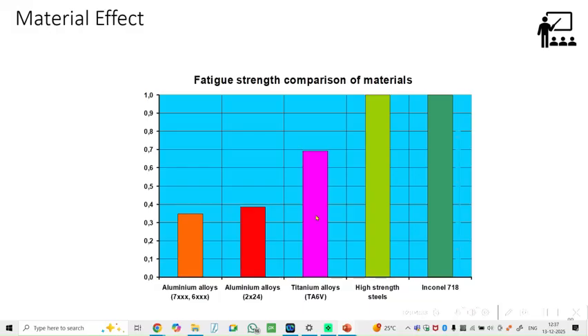Now machining. This is what I was telling you about, the skin pocket. You can use ordinary mechanical milling, but that's very hard. If it's a small piece, it's fine. When you're talking about a skin pocket, the sheet is meters in length and width, and you have to work specific regions. There is a term called the pad, where you fasten the frame and stiffener, but in between you have to reduce the thickness. The sheet is 2 mm, but 1.2 mm is sufficient in the skin pocket, so you have to remove 0.8 mm.